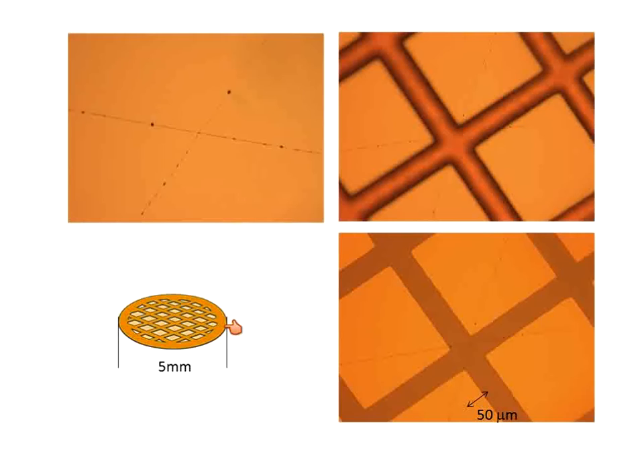Let's say that you wanted to measure the current or the IV properties of this junction. So you would take this TEM grid and place it in such a way that you shield or cover up this junction using this grid, okay? So that's a template, and you have covered it with this grid, and then you go ahead and evaporate your gold or silver, and then you take the grid out. When you take the grid out, you don't get any deposit of gold over here, but you do get a deposit of gold over here. And that's how we make our four connections to this nanofiber.